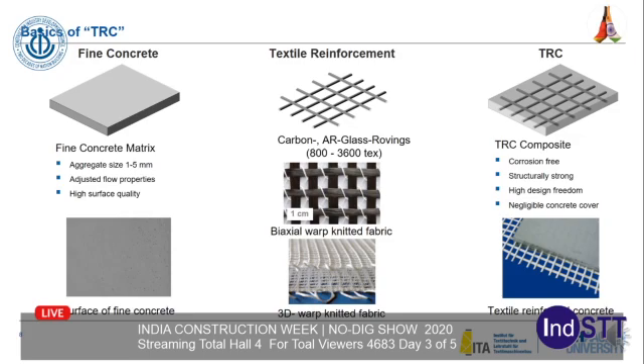The textile reinforcements are made of carbon or alkaline resistant glass rovings with titers up to 3,600 tex. These textiles are usually fashioned into a biaxial warp knitted fabric or a 3D warp knitted fabric, and both parts of the composite are placed together, resulting in TRC. TRC composites are corrosion free since the reinforcement does not corrode, dissimilar to traditional steel reinforcement. In addition, TRC composites are structurally strong because especially carbon fibers offer very high strength. They offer a high design freedom and a negligible concrete cover. So textile reinforced concrete offers many advantages over traditional steel reinforced concrete.